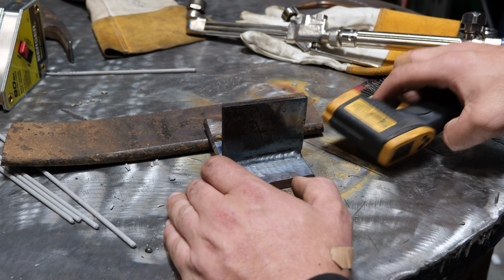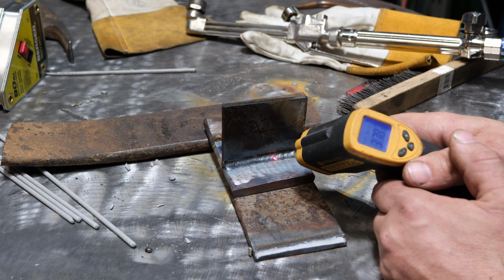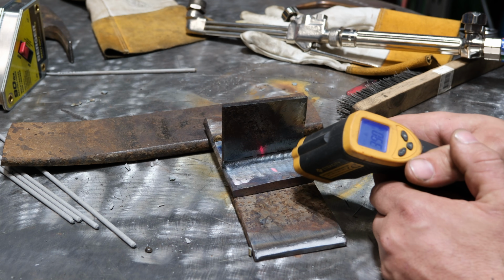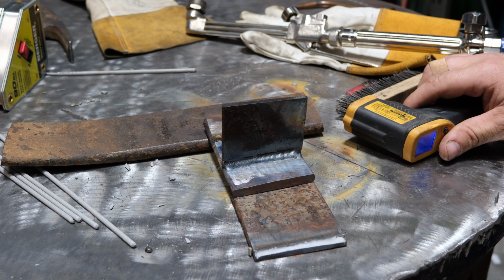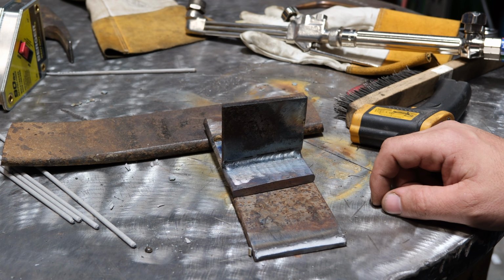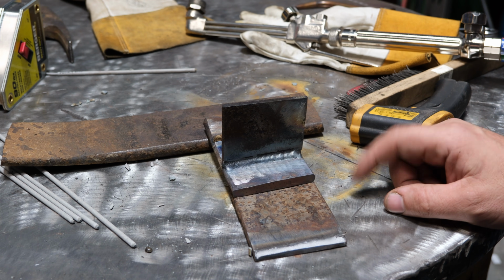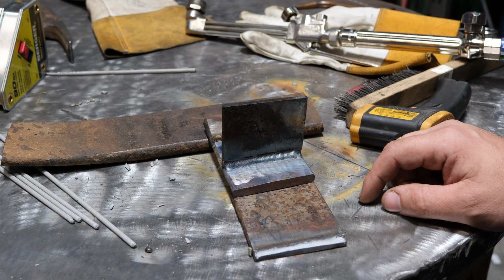Well, this thing's been sitting for a good 10 minutes already, and it's still at 400 degrees almost. So that's a good sign. You don't want this junk to cool fast. All right, well, I'm just going to let it air cool, and we'll come back, chuck it in a vise, and hit it with a hammer and see what happens.